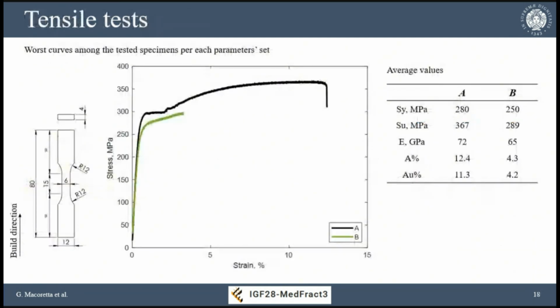Looking at tensile properties, the data for set A are more or less in line with literature values for strength and elongation at fracture, even a bit higher than suggested by the powder manufacturer. When we pass to set B, the material features lower yield strength and significantly lower elongation at fracture.